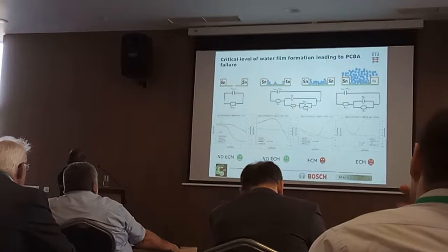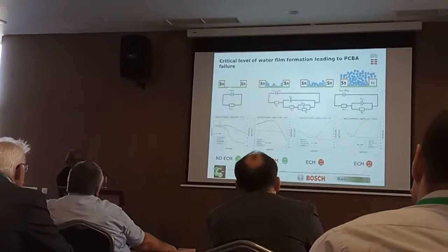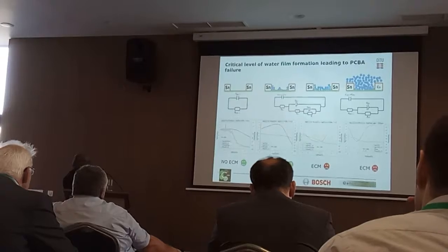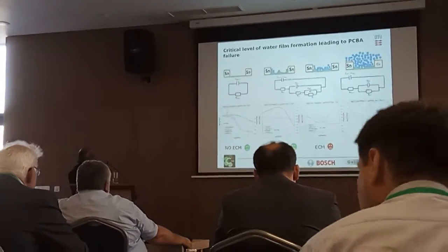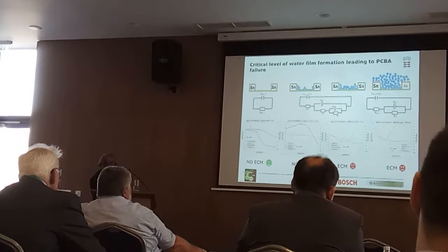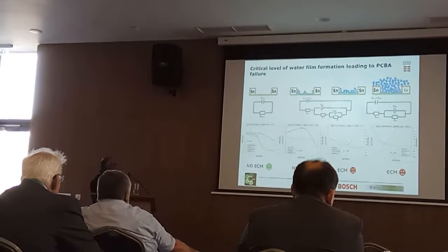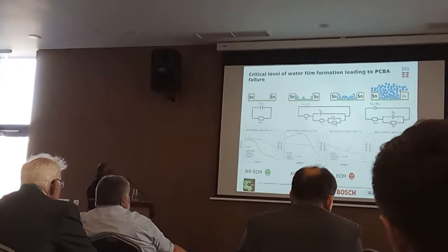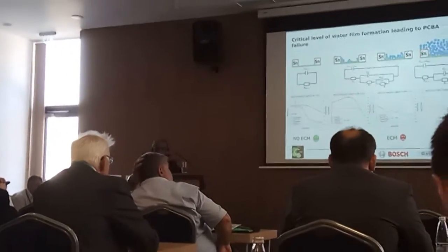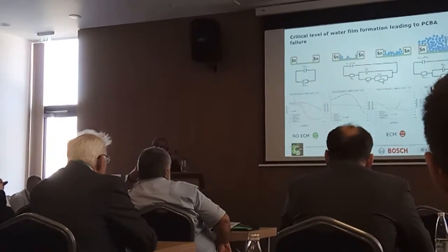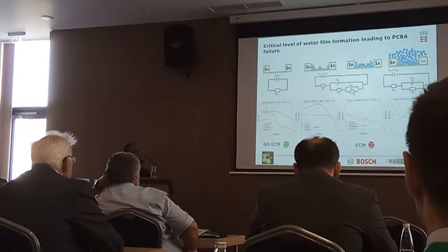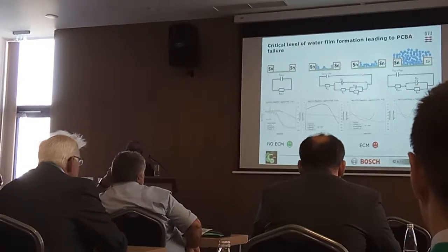If you look here, at atmospheric conditions, the water layer is at the nanometer scale. You can see the influence in impedance spectroscopy — if you take the high frequency side, it is like a capacitor. But as you increase the thickness of the water layer, you can see that when you look at the high frequency side, especially in the phase angle, it is changing from the capacitive mode to the resistive mode. This means that the water layer thickness reaches a level where charge transfer becomes easy through the water layer, and that is the point at which you start seeing failure in the electronics.